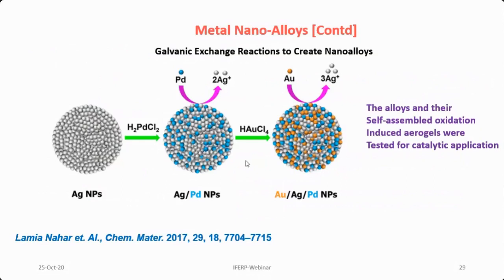So what happened is that some of the palladium 2+ was converted into palladium 0 by oxidizing silver 0 to silver+. So silver got oxidized and palladium got reduced. Silver acted as a reducing agent, and palladium got reduced. And those reduced palladium particles, by galvanic exchange, got into that silver cluster. So it became a silver palladium nanoparticle cluster. And this became a kind of alloy, because initially it was only a silver cluster, then it became a silver palladium nano cluster.